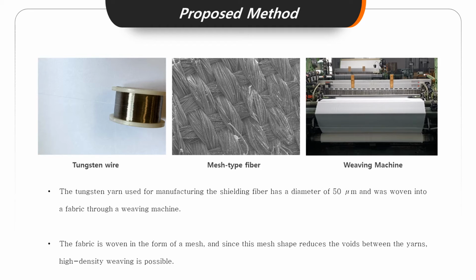The tungsten yarn used for the production of the shielding fiber has a diameter of 50 micrometer and it was selected in consideration of strength during weaving while maintaining the flexibility of the fabric. Since this weaving method reduces the voids between the yarns through the multi-layer structure, high-density weaving is possible. In addition, it has a structure that can be double-coated with the shielding material in the future. And therefore, it is possible to control the shielding performance by using a laminated structure or a double coating according to the radiation energy used in a medical institution.